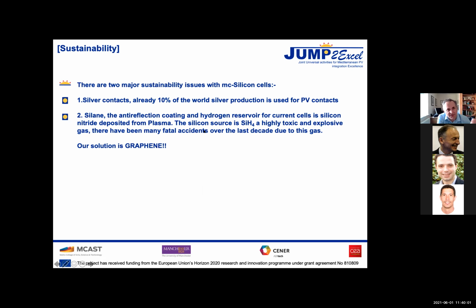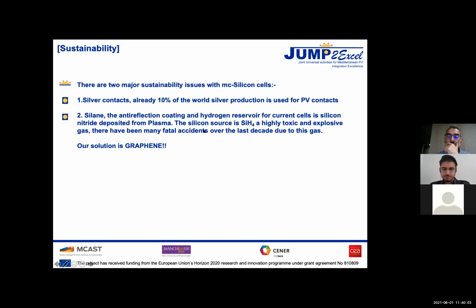The other one is not so much a sustainability issue, but undesirability. We use silane to create the anti-reflection layer and hydrogen reservoir. This is deposited from plasma. Silane is toxic, it's explosive. There have been many fatal accidents over the last few decades. In fact, there was an explosion at Tokyo University about 20 years ago now, which killed some academics. It's terrible. So people don't like it for obvious reasons. So if we can replace those two things, that's something we can do for silicon.